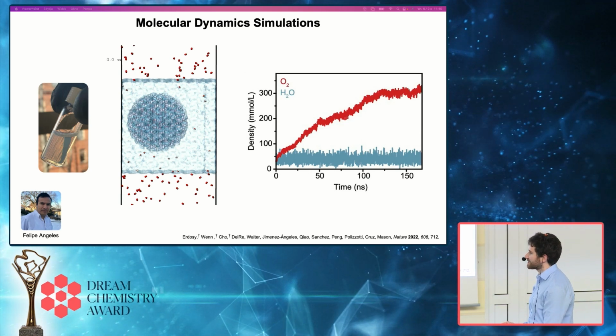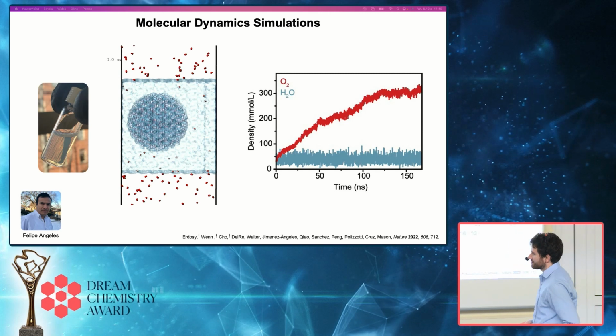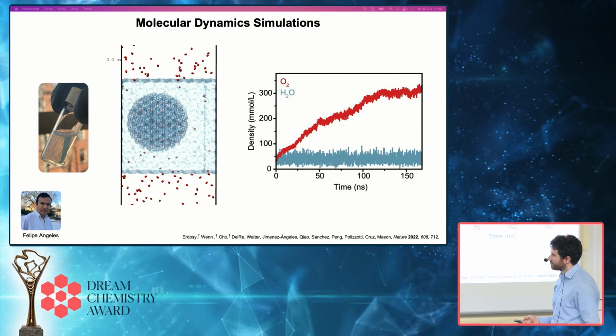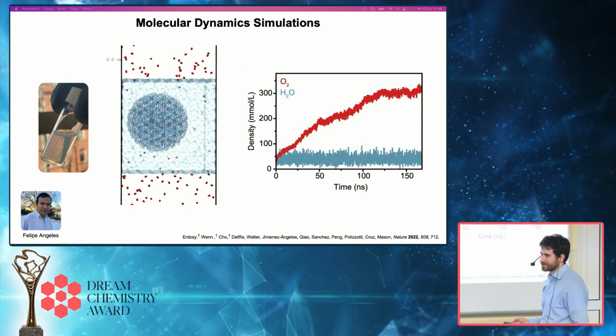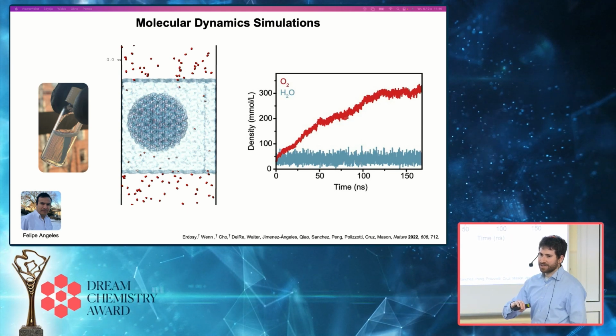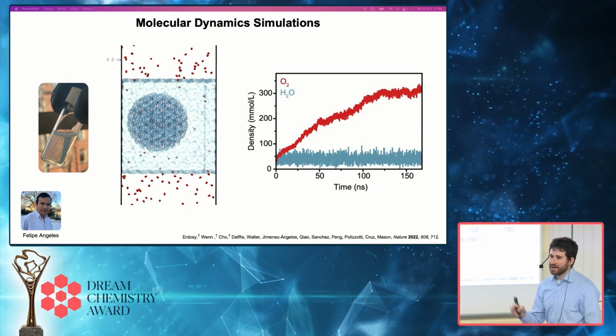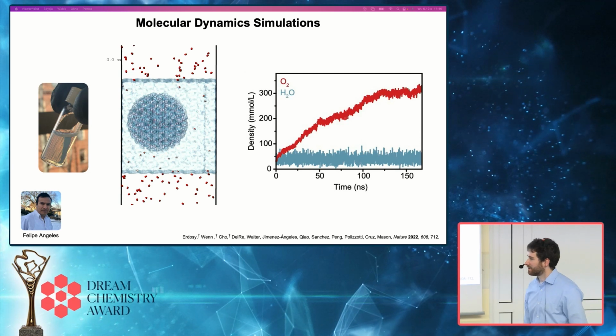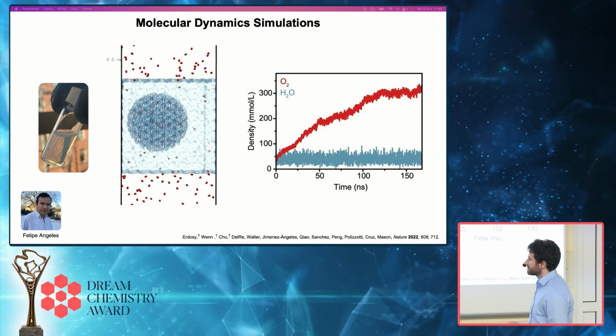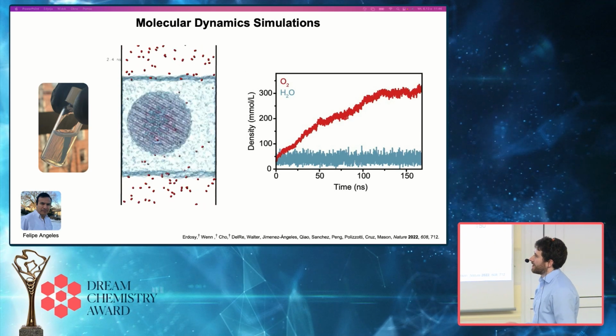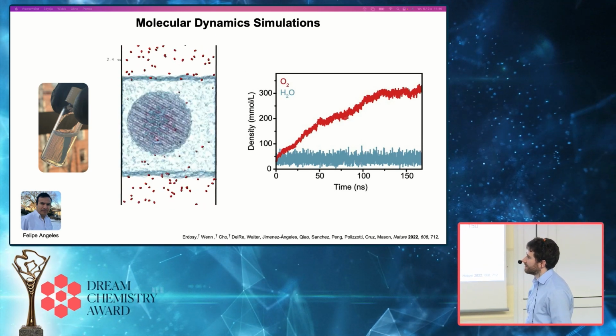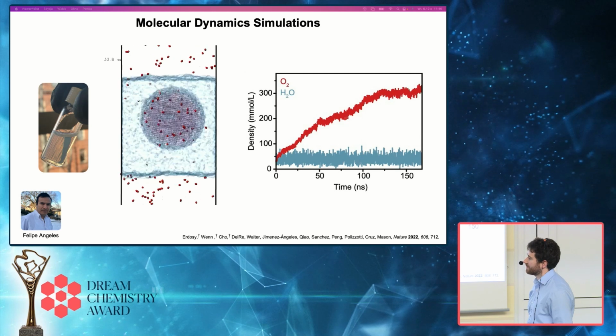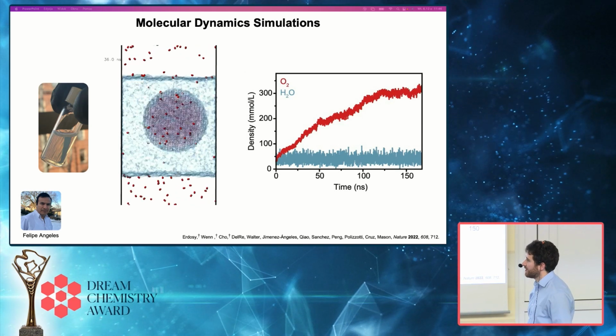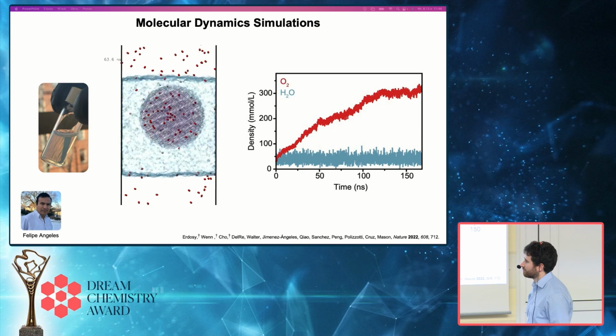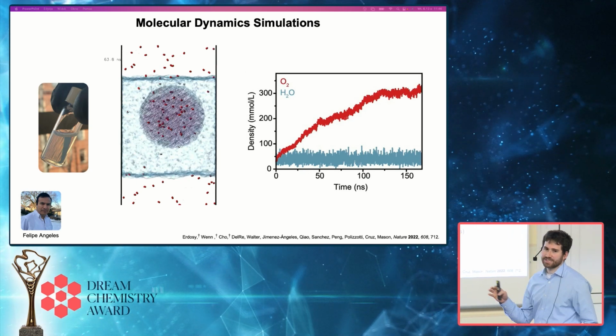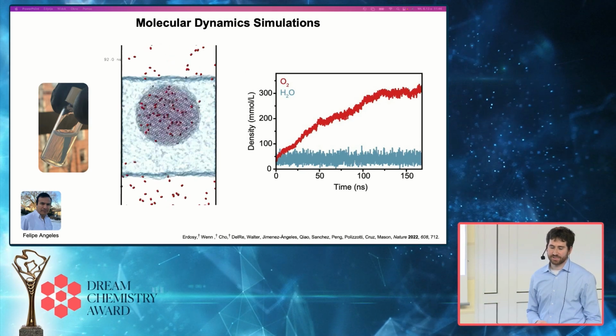This is just oxygen gas at about a pressure of 1 bar when the simulation starts. So it doesn't matter if we put water molecules inside the Silicalite 1 nanoparticle at the beginning or not. If they're inside, rapidly within a nanosecond, they're out of the Silicalite 1 nanoparticle. But what you'll see as we run the simulation is that oxygen molecules are rapidly moving around, and the density of oxygen, the concentration of oxygen inside the Silicalite 1 nanoparticle, will increase over time, while the density of water remains constant. Water stays out, but oxygen goes in and is absorbed.